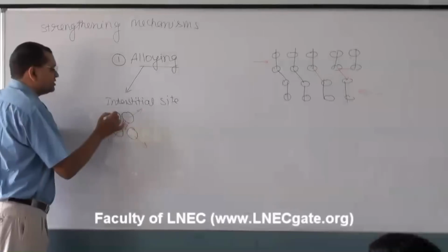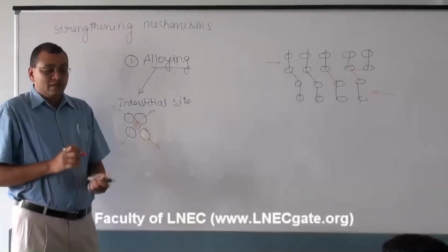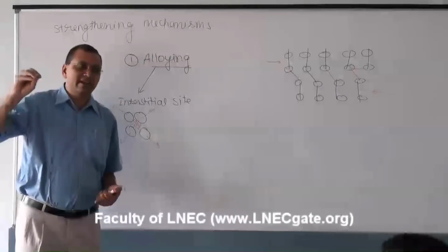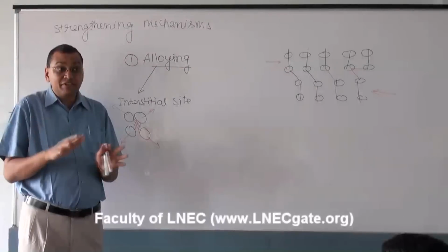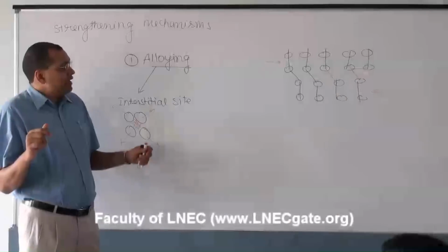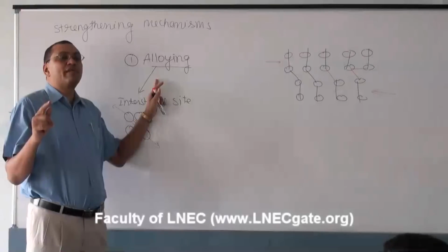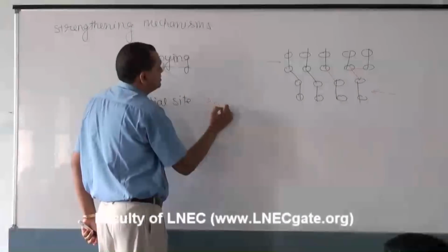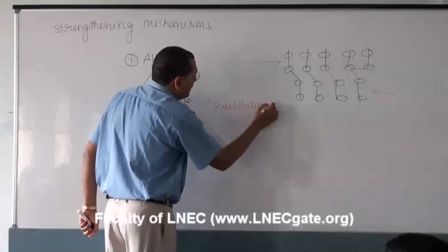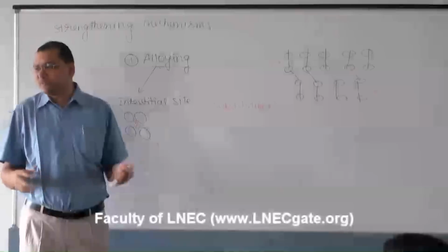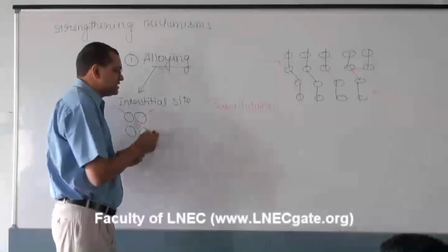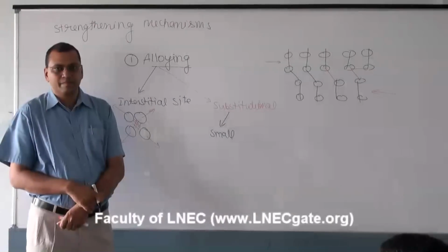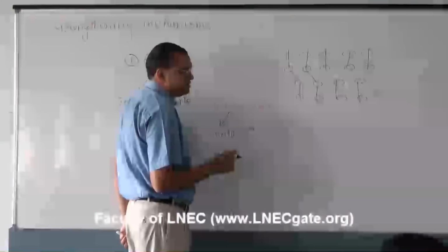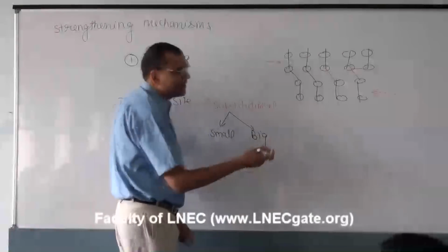So when the impurity atom fits in, these host atoms will experience compressive stresses. Suppose the space is not sufficient anywhere and some foreign impurity atom goes there, it will try to create a compressive strain field in the host atoms. And let us say the impurity atom occupies a substitutional site. Again there are two possibilities. One possibility is that the size of the substitutional impurity is small. Another possibility is that the size of the substitutional impurity is bigger than the host atom.